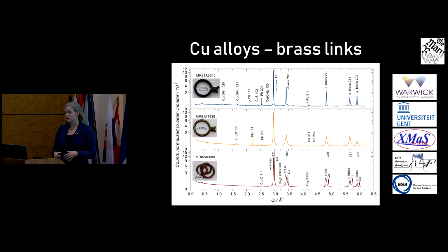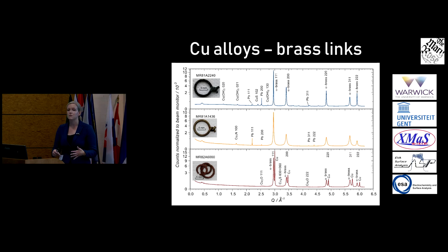So in the bottom pattern, you see here that you get a peak not only from the brass but also from copper, so this shows that the surface has undergone some dezincification. You can also see the one in the middle where it's much cleaner compared to the top one. The top one has much more corrosion products, and you can actually correlate this to the different treatments that were done to it, the different levels of cleaning that it underwent.